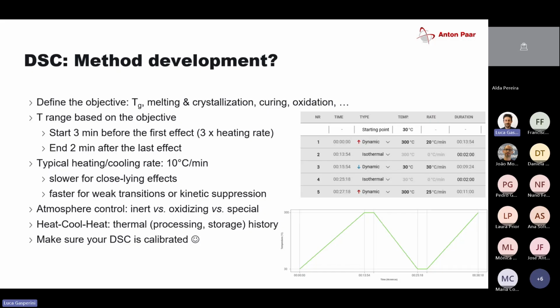Atmospheric control, I said that the furnace is actually purged with a gas of interest. In most cases, it's going to be an inert gas like nitrogen or argon. But we're sometimes interested in seeing the oxidation of the polymer or any other material, meaning that we would go for either air or oxygen. But there are some special gases that we can also use, like helium, which is a very highly heat conductive gas, and that also helps us with separation of close-lying effects, for example.